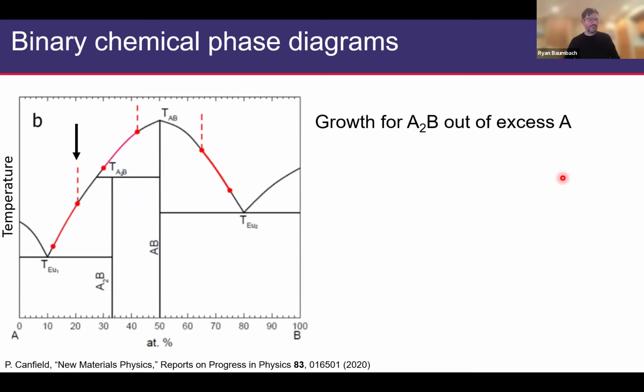Well, it might be that we want to grow these particular phases. And in this generic phase diagram, we have phases A2B and AB. We could make A2B by heating some powder in a pellet and make a polycrystal, as long as we stay below the peritectic phase. But that also might not be so great if we were wanting to grow a single crystal. So how can we grow a single crystal? Well, the short answer is that we can grow it out of an excess of element A. And this is your rudimentary principle when you're thinking about what a flux growth is. We'll return to flux growth a little bit later.